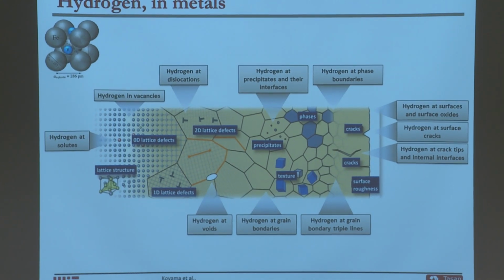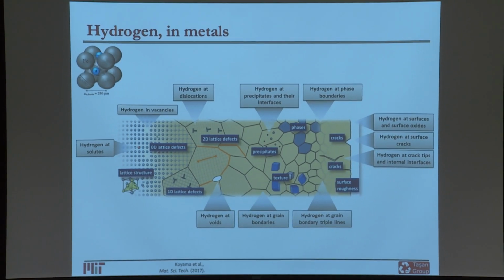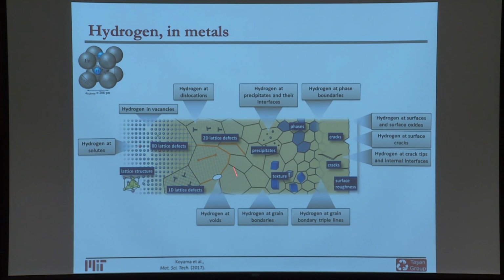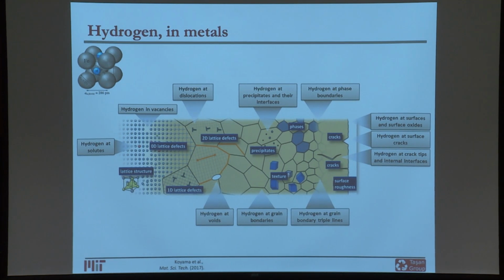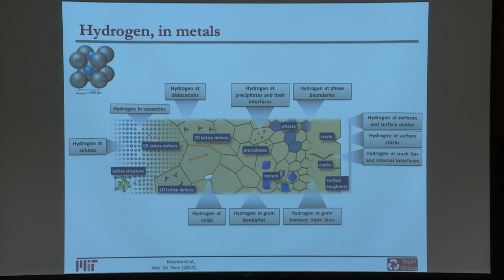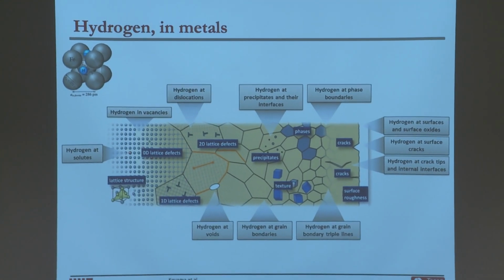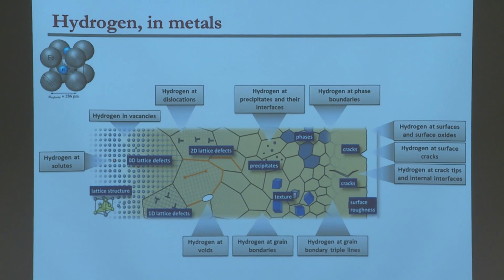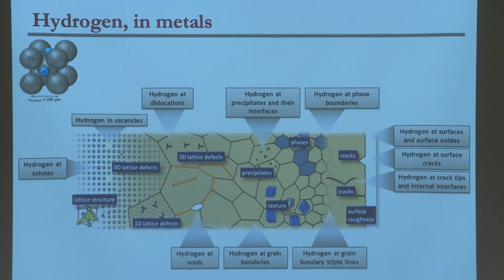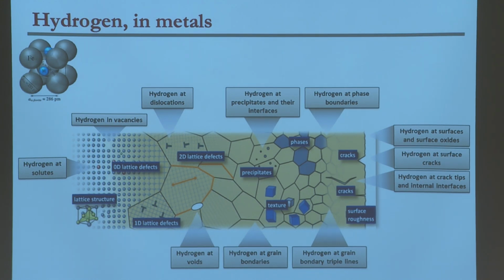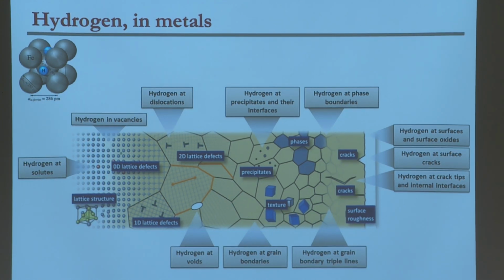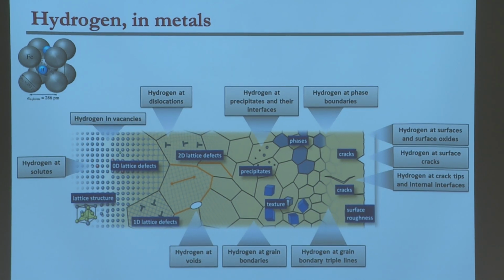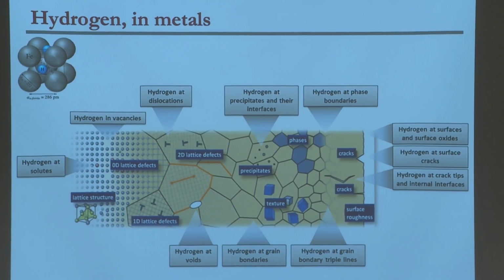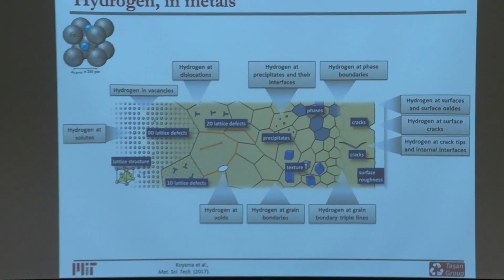So if you bring again the same microstructure cartoon here, what you can see is that in different materials, under different conditions, hydrogen can interact with each of these constituents in a different way. Surface effects, boundary effects, 1D defect effects, 2D defect effects, all of them are different interactions with hydrogen. And so it becomes difficult to understand what's going on. And keep in mind also that if you think about the periodic table for a second, hydrogen is on the upper left, which means that this thing is tiny. You can't even see this thing normally. There aren't even good experimental techniques to map where hydrogen is.